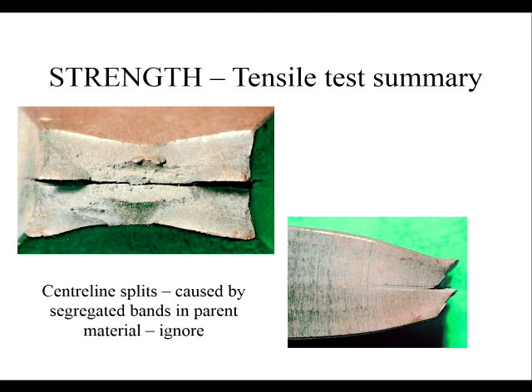You get a lot of information also by looking at the failures in these strap tests. So this is the end. These are the two pieces that have been pulled apart. This is the fracture surface, and they've been laid end to end so you can see them. And just by looking at that, you can see that down the centre of this steel pipe, there is a failure. There is a crack that's running through that. And this is caused by segregation bands in the parent metal layer. You may think that's a horrible failure. We can't have that. We must reject this. Actually, a thin band of segregation, which is in the plane of the pipe, doesn't affect the load carrying capacity of that pipe at all. And so generally, those are ignored, although they look pretty bad. If you imagine the top part and the bottom part of the pipe carrying all the load, and there's just this one very thin line down the middle, which isn't.